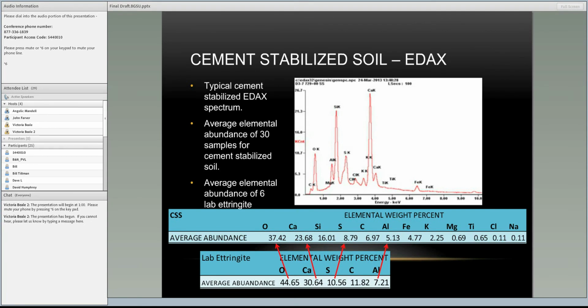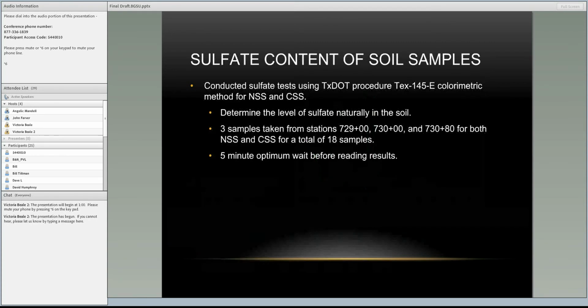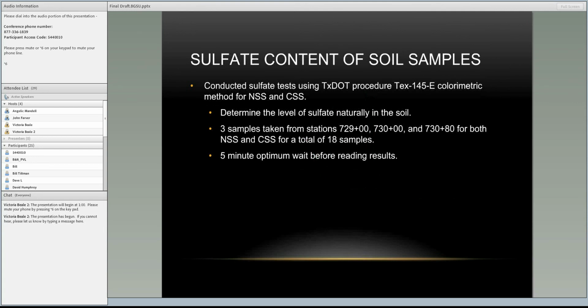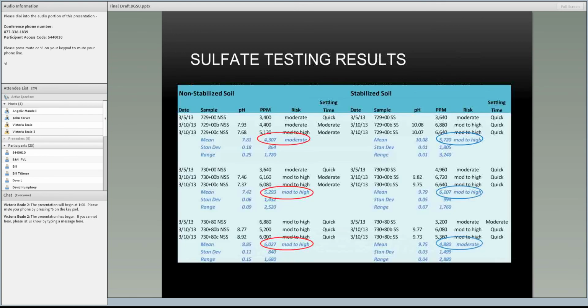We looked at 3 samples per station, so a total of 18 samples, and we used the 5 minute optimum wait time. So here's the results. On the left is the non-stabilized soil, and on the right is the stabilized soil. If you look at the non-stabilized soil, the pHs are around 7.9 or 8. And if you look at the individual sulfate levels, they're all over 3,000 parts per million. And the average is well over 3,000 parts per million for non-stabilized soil. With the stabilized soil, the same thing, all over 3,000 parts per million.